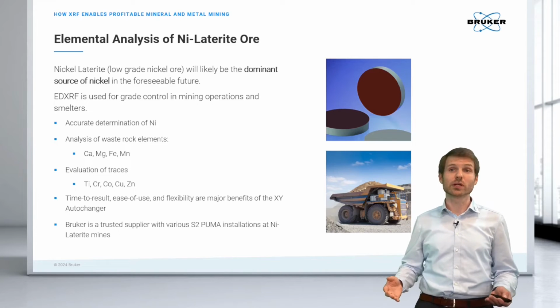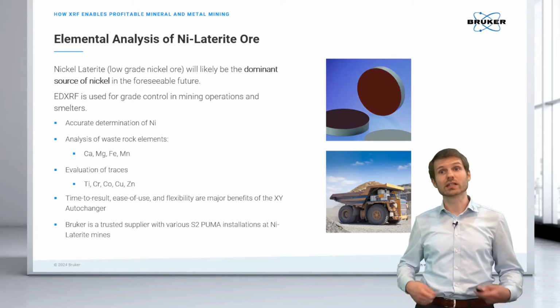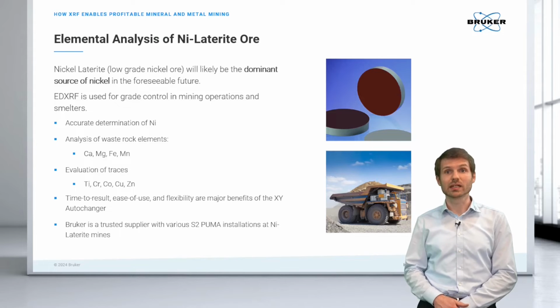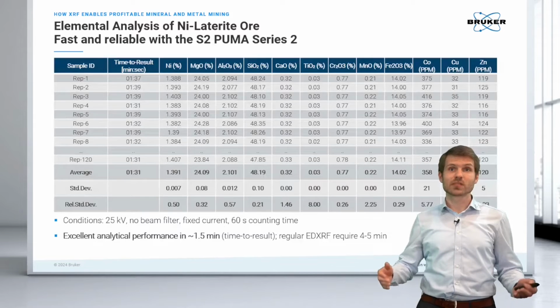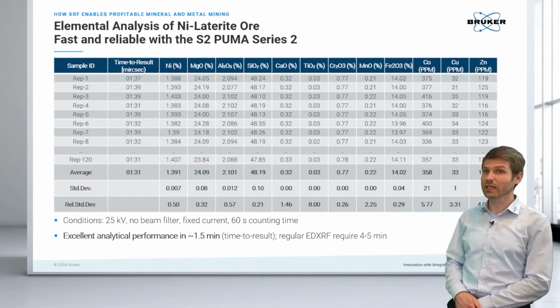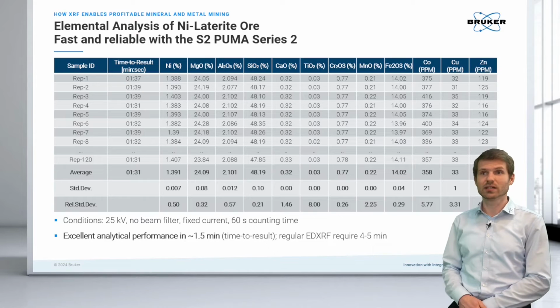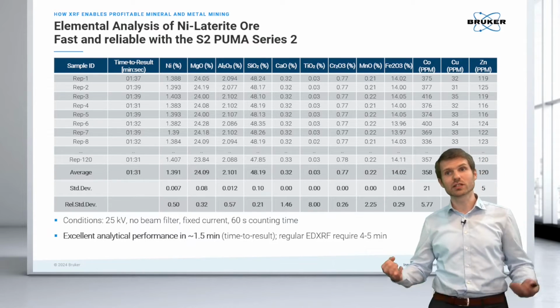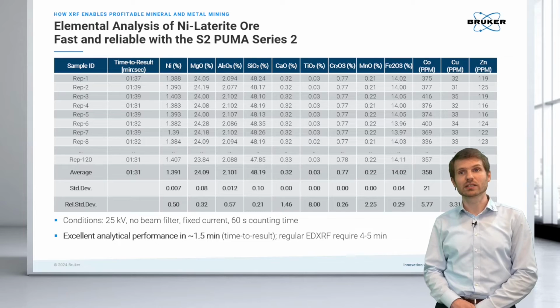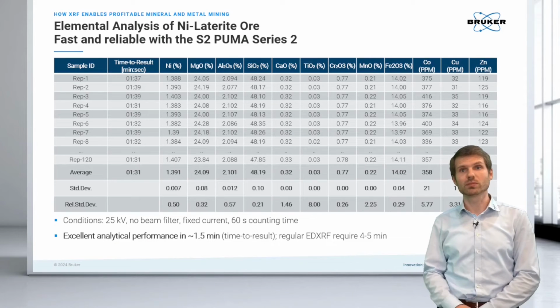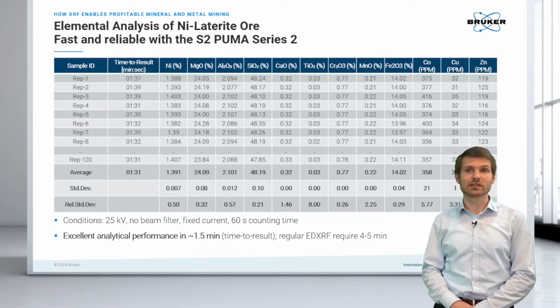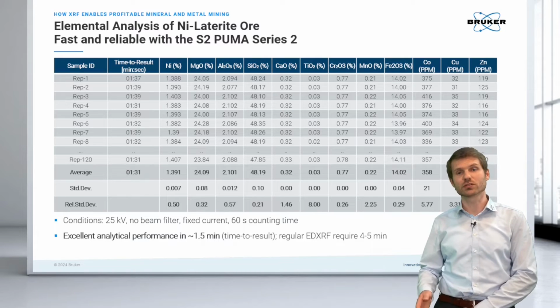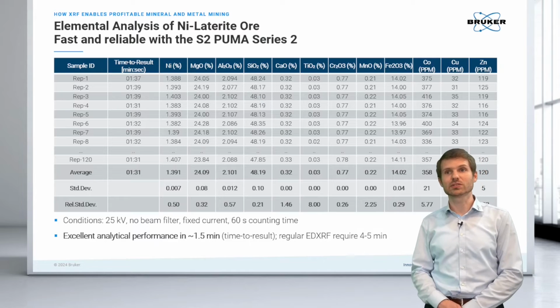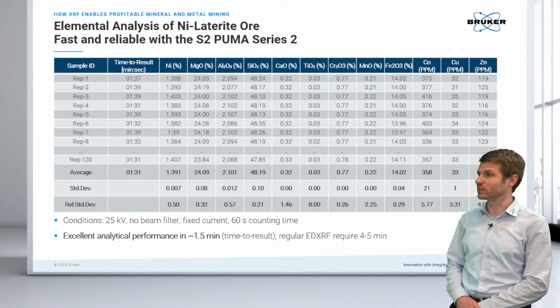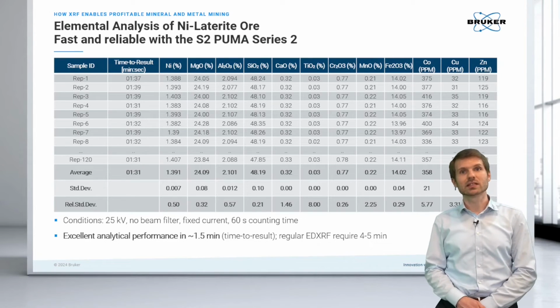So this is why pressed pellet is basically the way to go for this kind of analysis. And it's also very helpful if I have a device where I can load samples at any time, so an XY auto changer. So the S2 Puma Series 2, which is our energy dispersive system here, really excels. You can measure a pressed pellet from a nickel laterite mine or deposit in a few minutes, and this is really possible with our high-sense detector technology and our 50-watt tube. We can really get a high precision and accuracy within just 2 minutes or less from time to result.